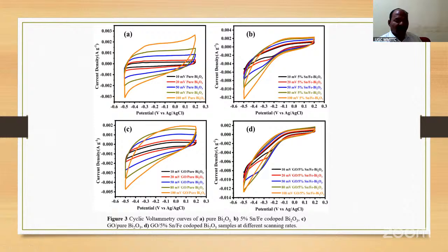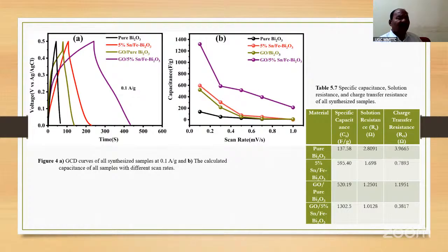Now you see this one, the cyclic voltammetry curves of pure, then the tin iron co-doped, and then the GO pure and GO 5%. Now you see this cusp here, from which we can find out the efficiency of the material. And you see here the galvanostatic charge discharge curves of all synthesized samples at 0.1 A per gram, and using this we calculated the specific capacitance.